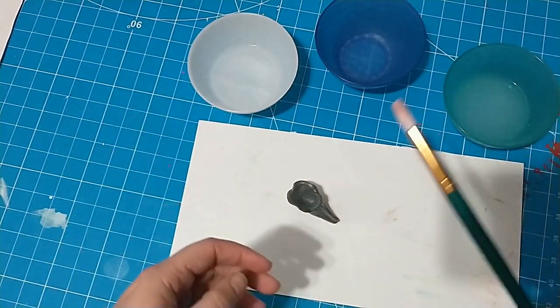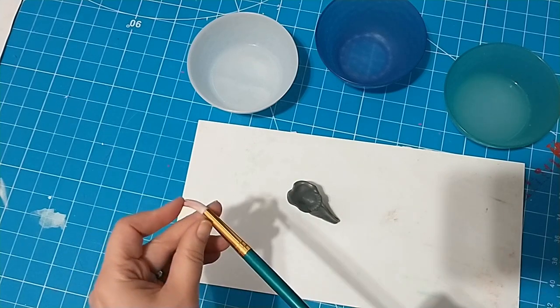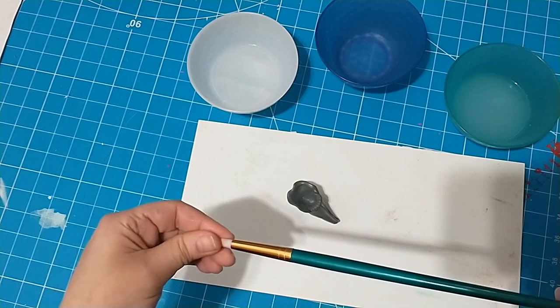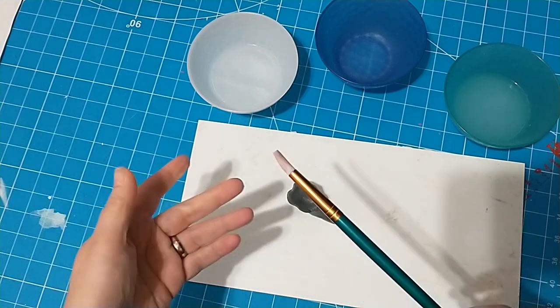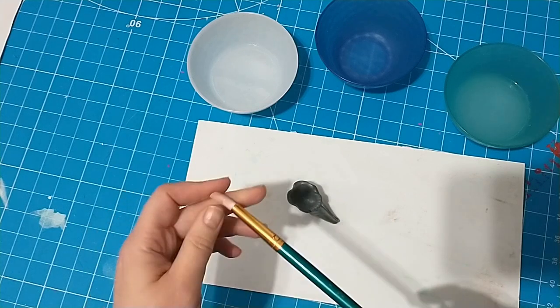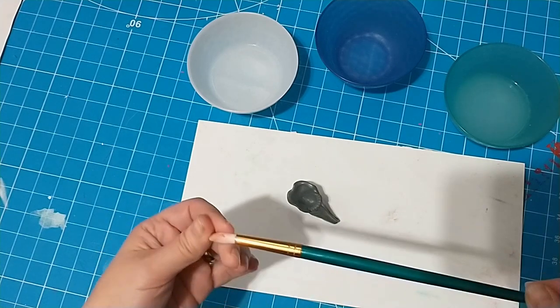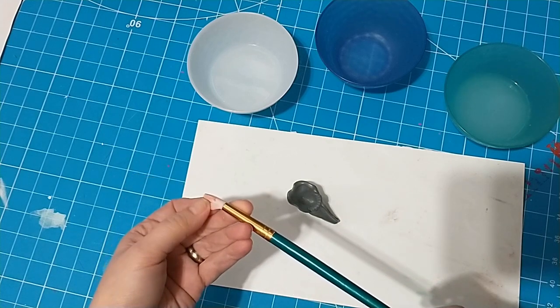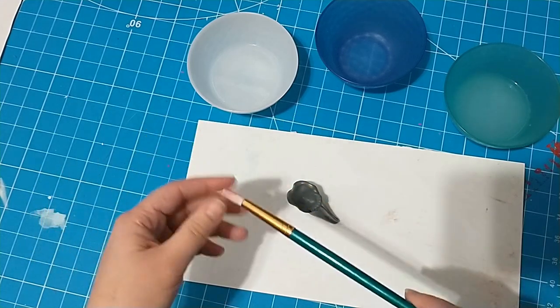Now, when I first started molding things, I used tin cure silicone. I used Smooth-On's OOMOO, which is a wonderful product, and the tin cure is much cheaper. However, tin cure is temporary. After about a year, I had to throw out all the molds I made with that stuff because they crumbled. They fell apart. Tin cure doesn't last. Tin cure is also not body safe, food safe. For stim toys, the fact that it crumbles and the fact that you shouldn't put it in your mouth or other orifices just means it's terrible.